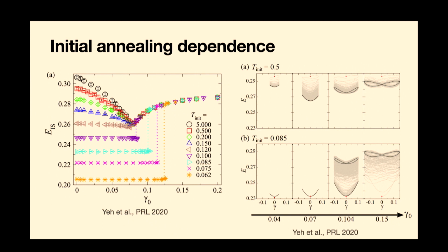It turns out for the well annealed samples, these are even more interesting because here it really depends on how you've prepared the sample, at what amplitude it actually starts to yield. Okay? So a system that's well annealed, you could strain up to a larger amplitude with almost no change in state and energy, until finally at some large amplitude it then becomes fluidized and reaches a fluidized steady state. Okay? So that's this interplay that I said of these two types of being out of equilibrium. You've got kind of the one type of non-equilibrium, the driving on this axis, and the initial non-equilibrium state on the other axis.